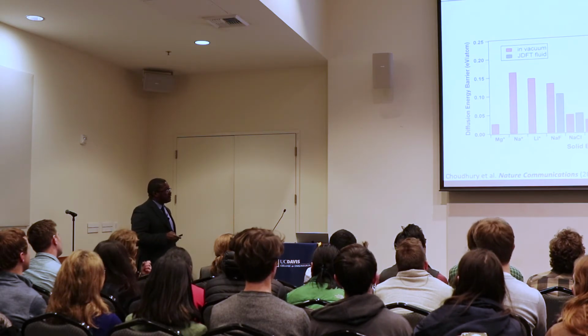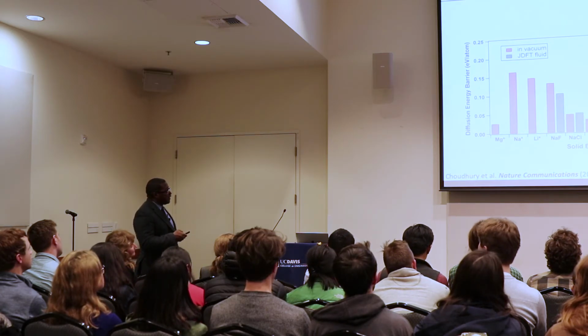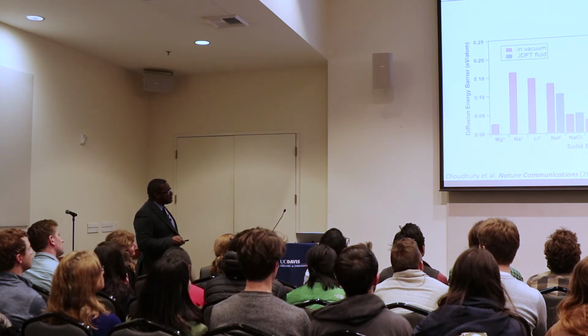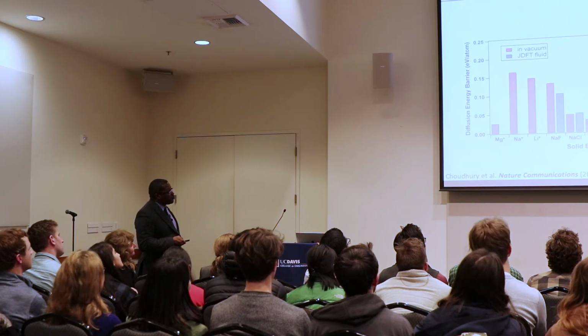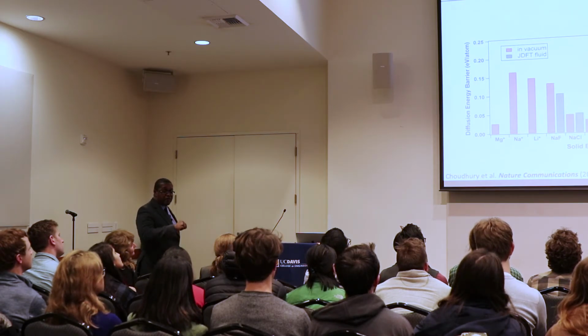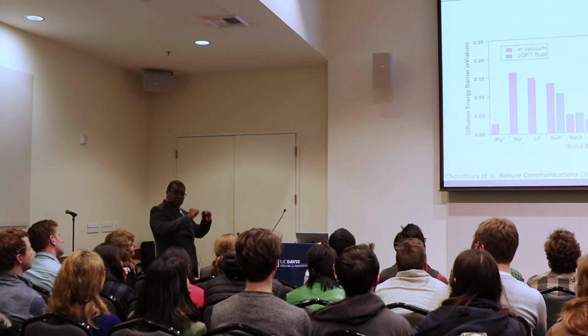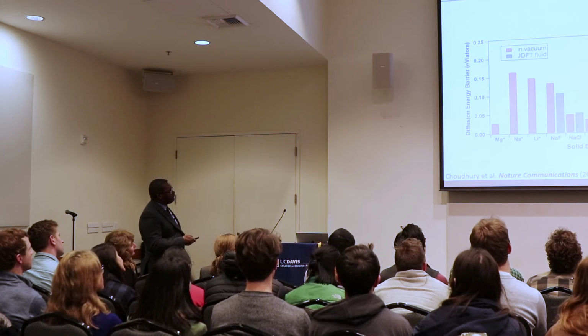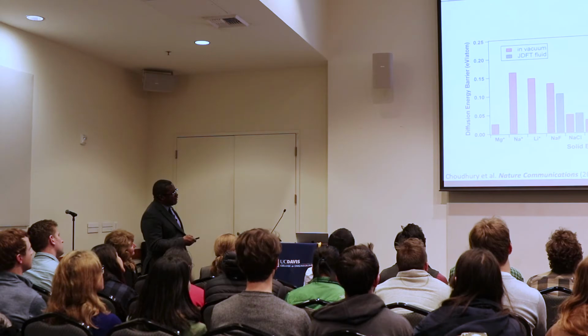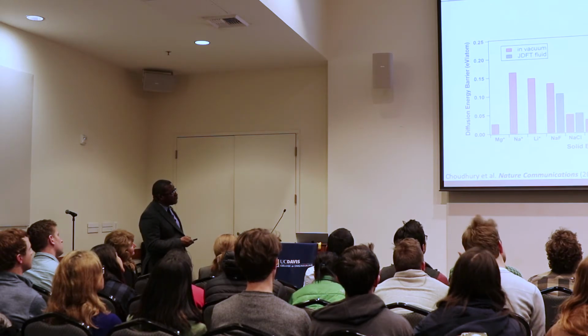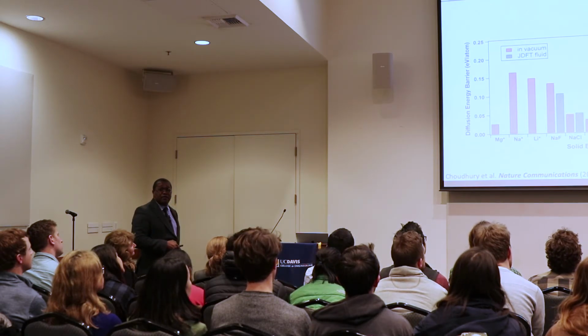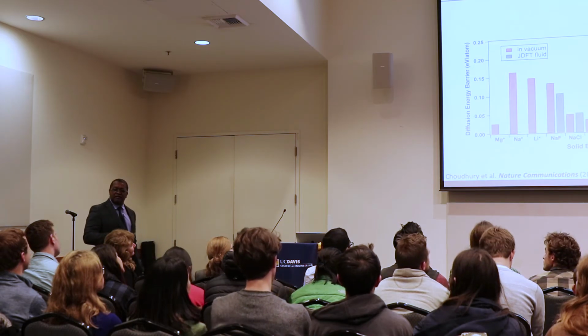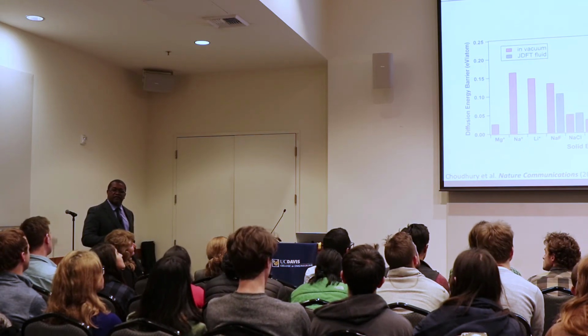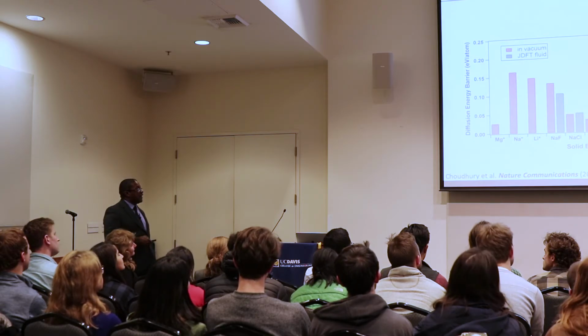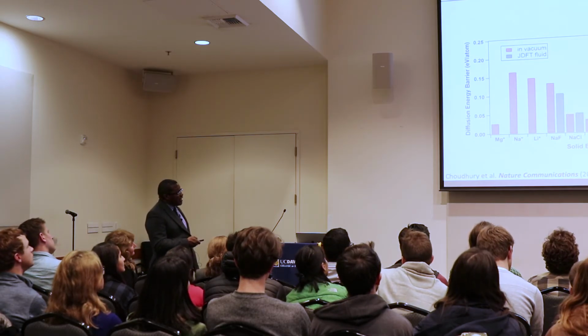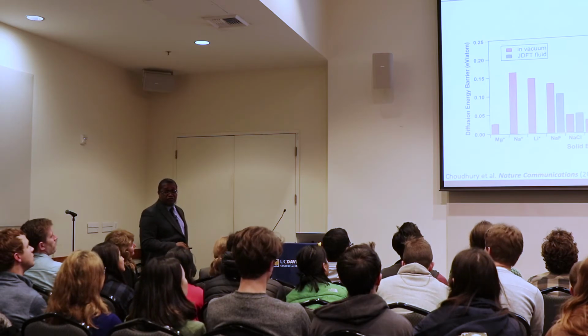The discovery that Choudhury and his colleagues made is that this lithium fluoride salt, if you compare the activation barrier for adatom diffusion on the lithium fluoride salt in a vacuum and in the electrolyte, is substantially lower than lithium carbonate, which is the electrolyte component typically present in larger fraction at the interface. If you use things like lithium bromide, the results are even more dramatic.